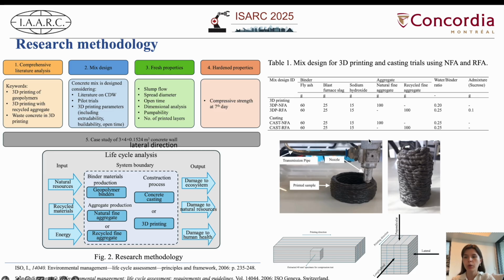mix design. We prepared four different samples, two for 3D printing, one with natural fine aggregate, and another one with recycled fine aggregate, and also two samples for casting with natural and recycled fine aggregates. Next, we evaluated the fresh properties of each mixture to assess printability and workability.